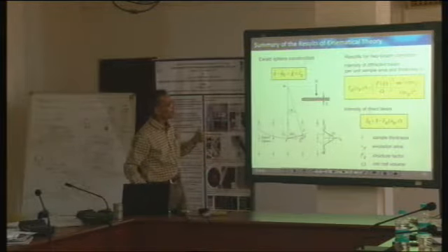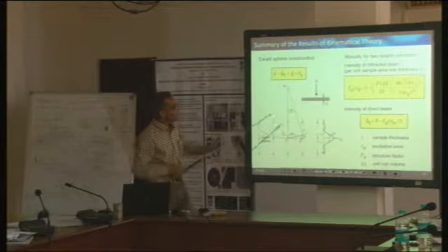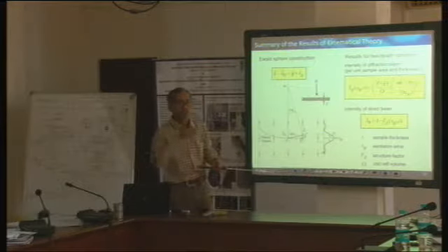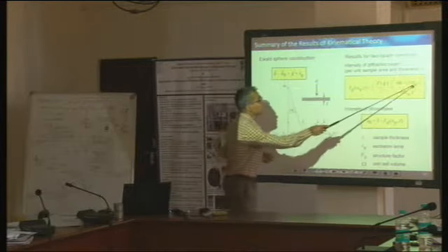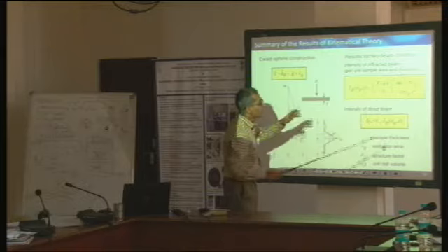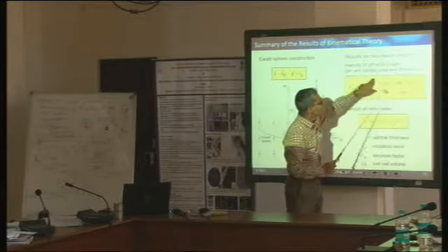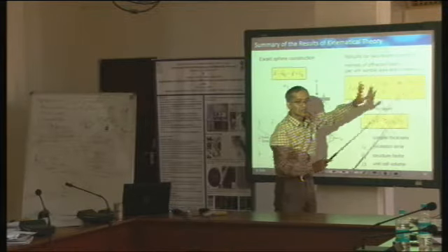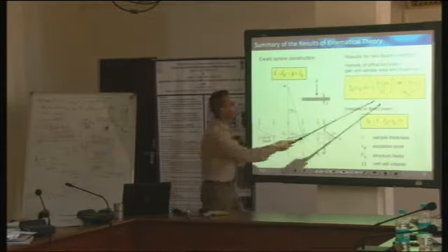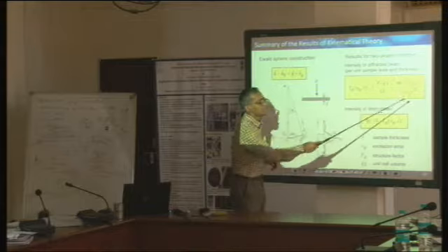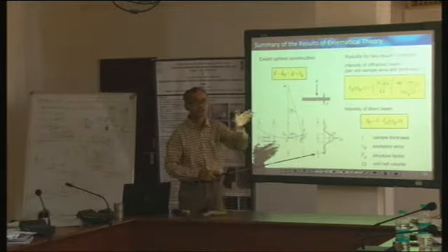How can we understand that there will be more intensity? If you look at this equation, if we substitute S equal to 0, or it tends to 0, you can do some trick wherein you put here t and here again t squared. So I divide and multiply by t squared, and this pi t s_g I give a symbol, let us call it theta.